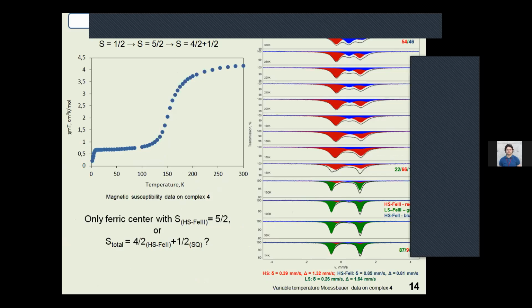Analogous to complex 3, similar magnetic behavior was observed in complex 4. Values are almost unchanged in the temperature range 300 to 200 Kelvin, and at lower temperatures demonstrate a sharp decrease to reach a plateau typical for the low spin ferric configuration. A slight deviation of the obtained low temperature values can be explained by the presence of about 10% of molecules trapped in the high spin ferrous state at this temperature. It should be noted that the analysis of the magnetic susceptibility data does not allow one to unequivocally distinguish the two possible ferric catecholate and ferrous semiquinonate electronic configurations, which are characterized by the same multiplicity.